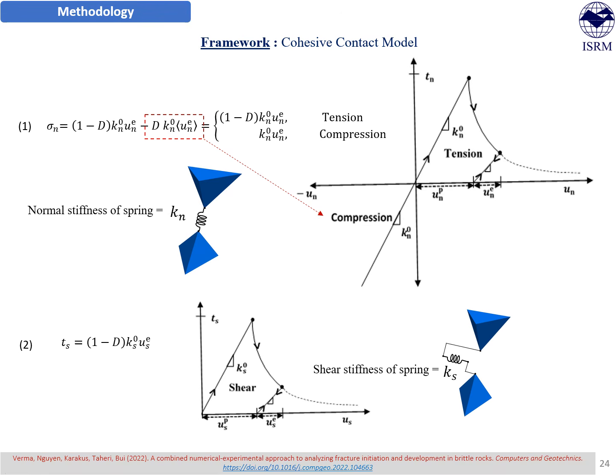The contact model under tension in post-peak behavior results in gradual degradation of strength, unlike the immediate drop shown in various available models in 3DEC and in other published literature as well. And the same goes under shear as well. The post-peak strength of the contact degrades gradually, and that degradation corresponds to the damage, and the magnitude of damage not only controls that degradation but also degrades the elastic response as well. So you can see that before peak we have a certain stiffness, and that stiffness reduces with damage in the post-peak response, which is captured by this contact model in a true sense.